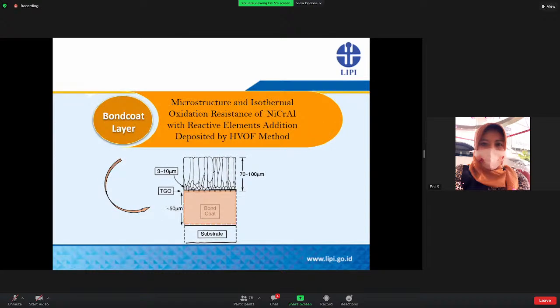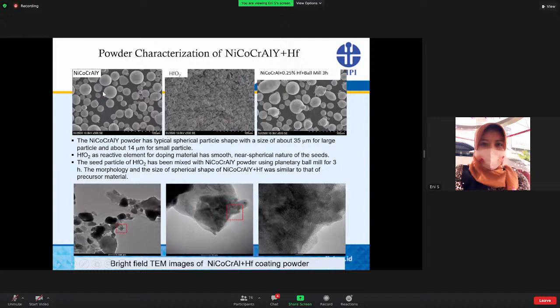So in the next slide, I will discuss the results in microstructural and isothermal oxidation resistance of nickel, chromium, aluminum with reactive element addition deposited by the HVOF method. Initially, commercial powder of nickel, cobalt, chromium was used as a coating material for the bond coat layer, as shown in these figures. This nickel, cobalt, chromium, aluminum powder has typically spherical particles with a size of 14 to 35 micrometers.